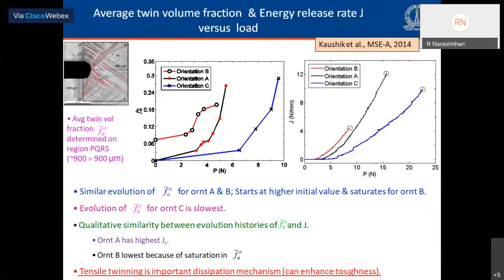Now, if you examine these two figures, you see a qualitative similarity between the two. In particular, if you look at the twin area fraction evolution for orientation A and B, they are similar, except that in the case of orientation B, you will see that FTT, the average twin area fraction, starts from a finite value. This is because there are some polishing twins present in the specimen, as I mentioned. And also, it tends to saturate early, and that is owing to the impediment caused by the polishing twins to subsequent twin development. This also led to premature failure, as you can see on the right side.